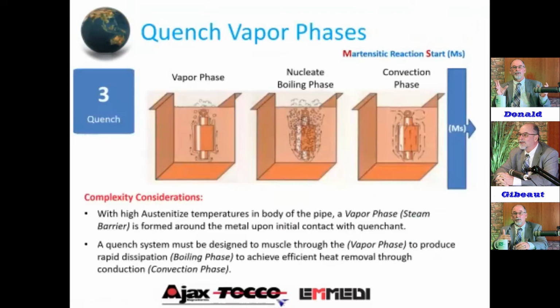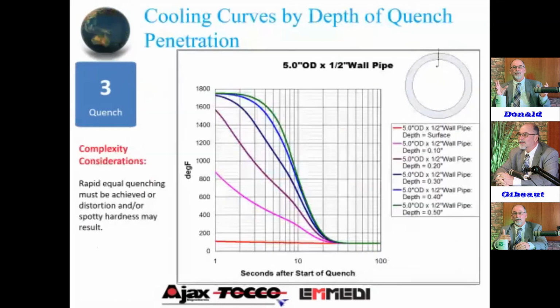The real work is done. And one of the main elements right out of the gate is you have to power past a vapor barrier. I mean, it's like any piece, something hot, and you stick it in or pour water on it, it's going to dance on the surface. So you have a vapor barrier that you have to power through to get to that MS point first. So now you see that aggressive TTT curve, and then you have a condition where you're not actually quenching until you power past this vapor barrier.